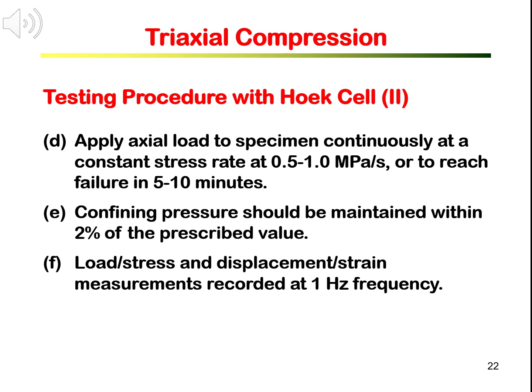Then we continue to apply axial load to the specimen at a constant stress rate of 0.5 to 1 megapascal per second, or to fail the rock in 5 to 10 minutes. Throughout the axial loading, confining pressure in the triaxial cell should be maintained within 2% of the prescribed value. While loading, record load or stress and displacement or strain measurements at 1 Hz frequency.